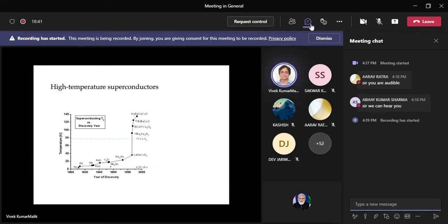And all of a sudden, Karl Müller and Bednorz discovered superconductivity in this lanthanum barium copper oxide, which is an oxide material. If you take the parent compound, they doped or substituted lanthanum with barium to a certain extent. So the parent compound lanthanum copper oxide, La2CuO4, is an antiferromagnetic material. So they doped it. Of course, magnetism was gone, which is still actually true as a rule. So lanthanum barium copper oxide was non-magnetic, but it's an oxide, and since the parent compound was magnetic, no one expected that it could be a superconductor.